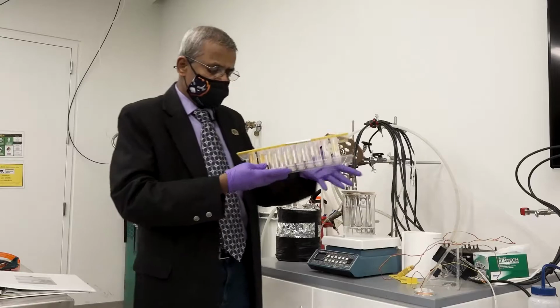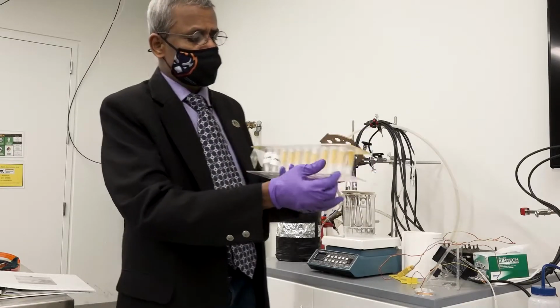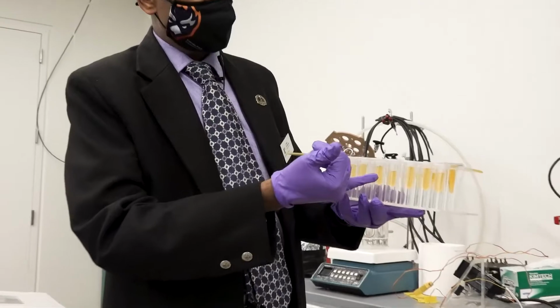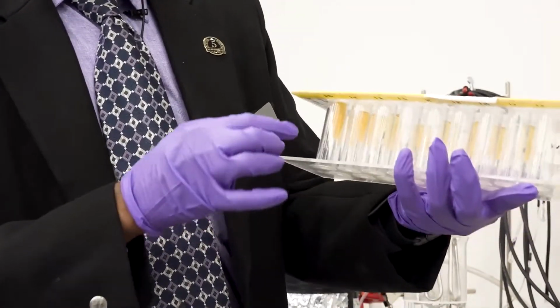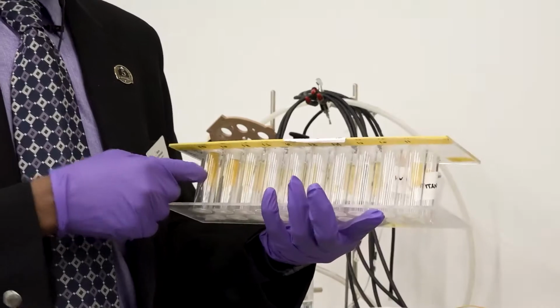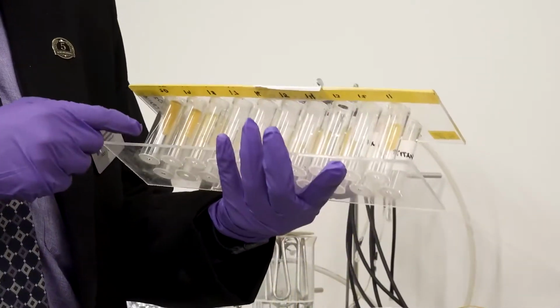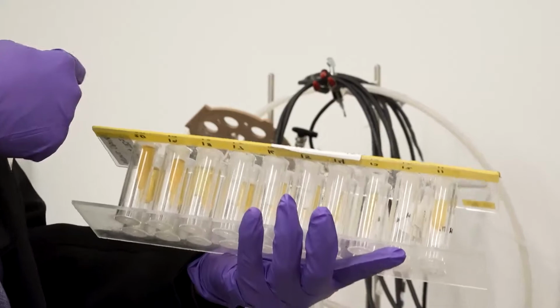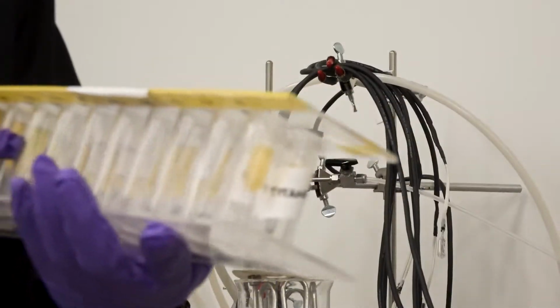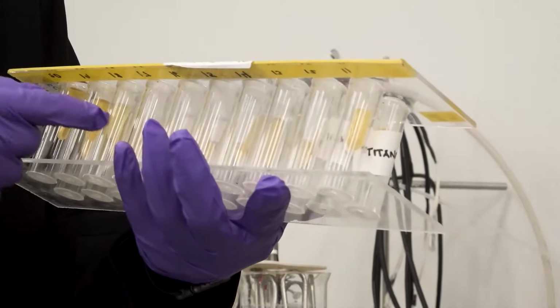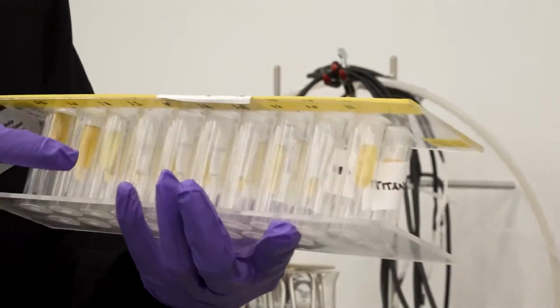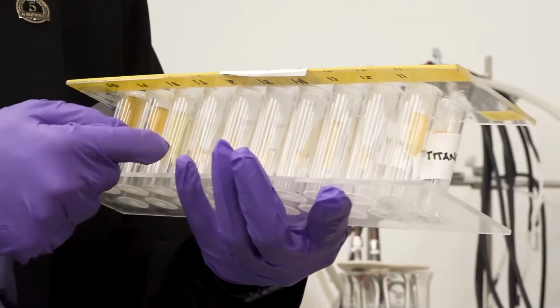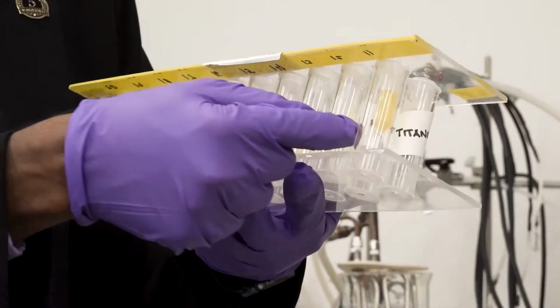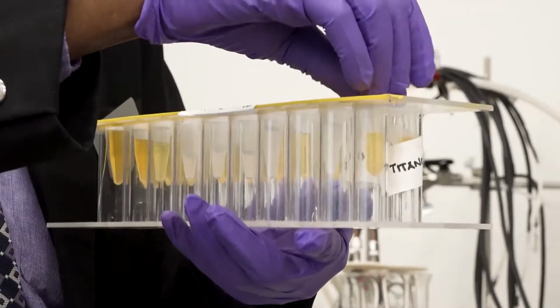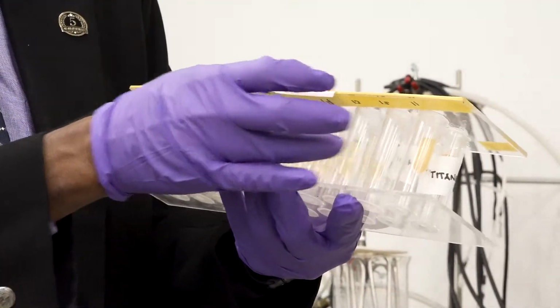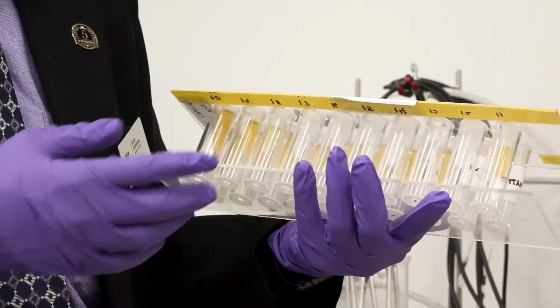So when we start with our contaminated water, what you see on the green and the yellow color contaminated water, we try to use a contaminated waste stream of water. Now we are also trying with a leachate from the landfill. Then we try to use this batch reactor under the sunlight or the UV light source and the photocatalyst. You see there is a discoloration or decoloration of the methyl orange. That's like a model contaminant. It goes, and then at the end of the day you will get the clean water, or at least the water which you could use for irrigation purposes.